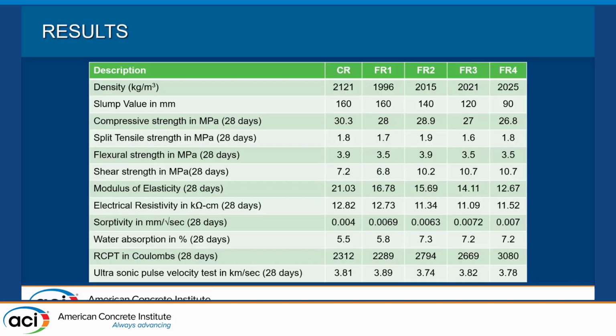Now seeing the results, the first major impact was the density, as our objective was getting semi-lightweight concrete. We got it in the range of 1996 to 2121 kg per meter cube. Conventional concrete, as you all know, is around 2400 kg per meter cube. We have reduced the density by around 300 kg per meter cube, which is a huge chunk. Second, with an increase in fiber content in the samples, we saw a decrease in the slump value, but it was still a moderate slump value, which is good workable concrete.